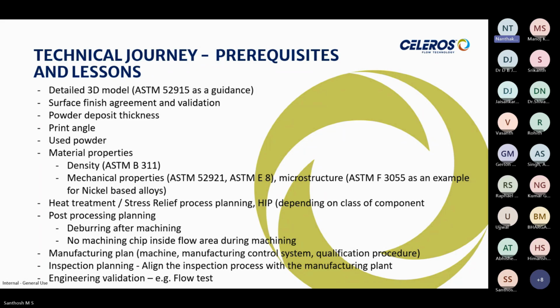So the first thing that we did was to print a small segment, because after printing we will not be able to see the inside finish. So we printed a small segment, and we checked the surface finish of those particular flow areas, and then we sent it to a Houston facility, and we validated it. What I'm saying here is there are some components where the surface finish can be improved after you make the component, but this one we cannot do anything like that. So we needed to take steps prior to building the component.